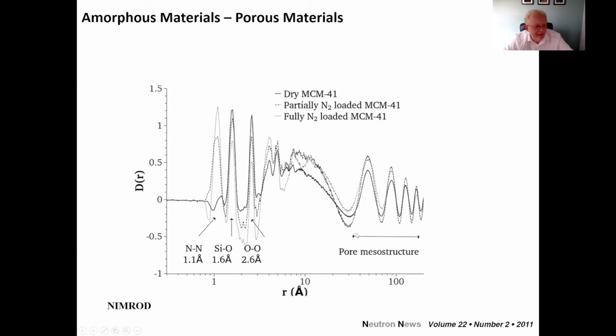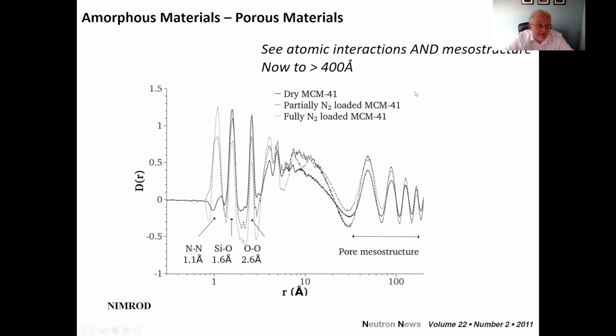But what we see out here, we see changes in these peaks which correspond to the void space within that mesopore. And from these lines, as these lines increase in intensity, we can see that these pores become progressively more filled, and we can use this information to calculate the amount of filling within the mesopore. And we can do all of this experimentation within a single experiment, and we can do it dynamically on a minute time scale as well. So we see the atomic interactions and the mesostructure out to about 400 angstroms, dynamically as well.